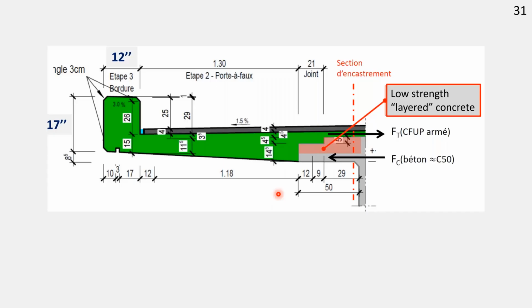So let's have a look at this cantilever slab in UHPFRC. In green here, we've reduced the size of the curb to the minimum necessary. And this is a significant difference to curbs in reinforced concrete that would be much thicker and much fatter. And I use this drawing also in order to explain one little problem we had. Actually, during the hydro jetting, the workers found that here, this domain in red of the existing concrete was like a layered concrete with relatively low strength.